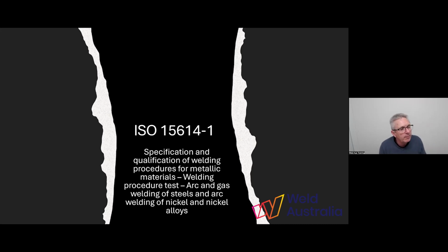Then we might have to look at other options where we can make it compliant, maybe a tensile test on a butt joint. We could do a butt weld, and then use a tensile test and a hardness test, and they will automatically qualify it without X-ray or ultrasonic, because they'll give us the range, they'll give us the options, and we're allowed to do that.